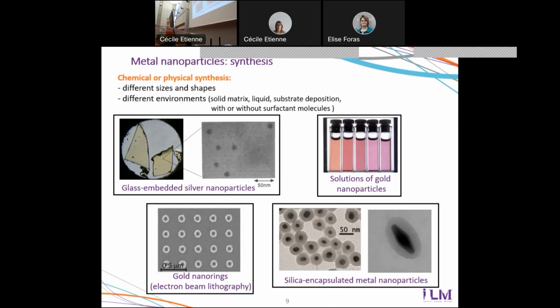And here, it's still colloidal particles, but it illustrates the fact that chemists are now able to produce quite sophisticated objects. So for instance, these are nanoparticles with a metal core and a dielectric shell, silica encapsulating the nanoparticles. And here, it's also a core-shell nanoparticle, but with a more complex shape because it is a bipyramid of gold.